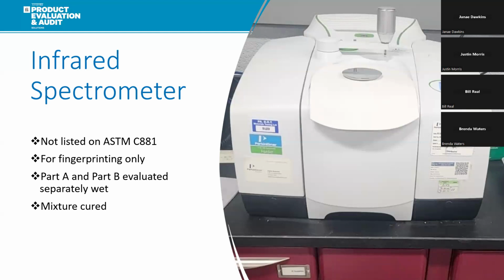Now, testing by infrared is just a fingerprint. It's not in C881 and it's not in M235, but a lot of people, including PennDOT, use it as a fingerprint. That's all you want to use it for. For example, a company has the contract for the epoxy product, and you take a fingerprint of it. Somewhere down the line, you start having issues with the product. Well, you get the product in again and you retest it. So in the fingerprint, you're looking for peaks that may be present that weren't there before. You want to look at the intensity of the peaks. You want to look at whether peaks maybe shifted to the left or to the right. So this acts just as a fingerprint to have for your records.